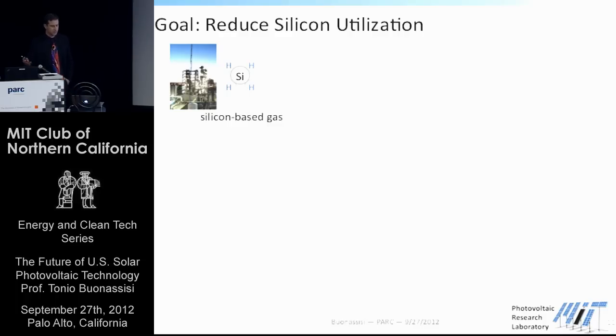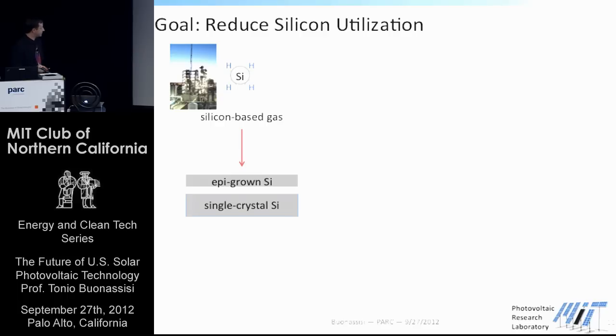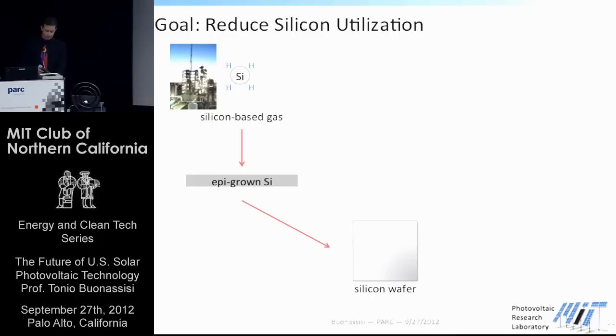So what is the goal here? The goal I mentioned, we have to reduce our silicon utilization by about 5x. One process or one idea that has been imagined by engineers and scientists and is now being reduced to practice by several companies is to start with the silicon-based gas, the silane gas, from the distillation process that I mentioned, to go directly to deposition on a seed. So the seed is formed with a single crystalline layer with a little buffer, and then the epi layer is grown from this gas directly on that seed. The seed is removed, and the single crystalline substrate is then reused for another process. And we have this very, very thin layer of silicon grown without any sawdust, without any kerf loss, and that forms our wafer.